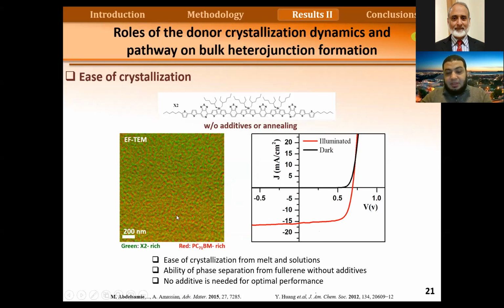And we can see here for this X2 material, we can get a very high performance because of the ease of crystallization, and we can get phase separation very easily without any additives.